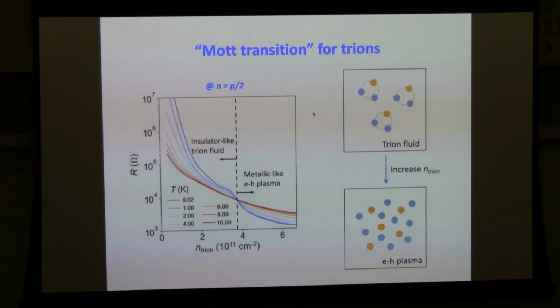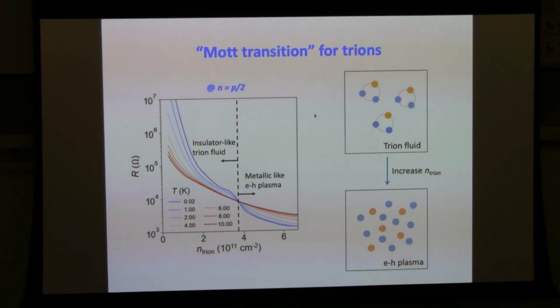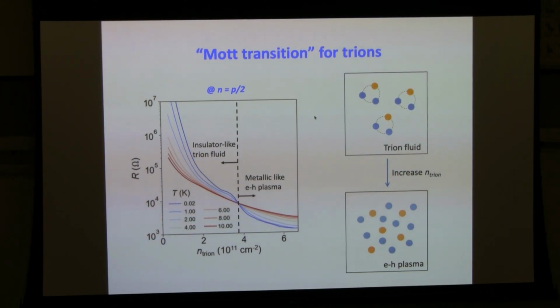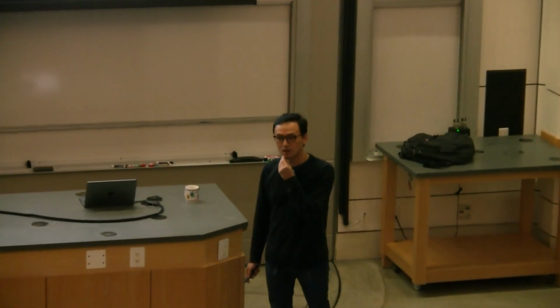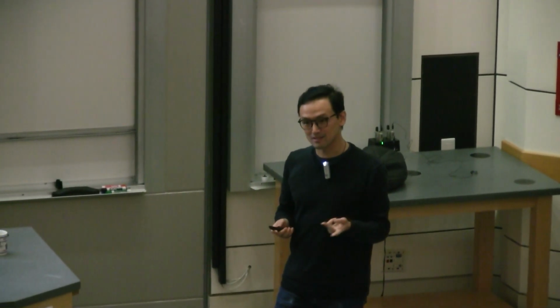Could you please explain why the tungsten and the molybdenum layers were used for the hole and electron layers in the schematic rather than some other materials? Oh, why just molybdenum selenide or tungsten selenide? We want to choose a type 2 band alignment, so the conduction band minimum is in one layer and the valence band maximum is in the other layer. You can actually choose other materials as well, like molybdenum telluride for the electron layer. That should also work. But we picked these two because they are the cleanest materials among the TMD family, so they have a very low density mobility edge.